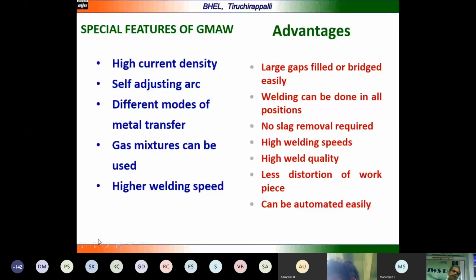There are 3 different modes of metal transfer in this process, which we are going to see in the subsequent slides. Gas mixtures also can be used in this process, and higher welding speed can be achieved. One major advantage of this process is we can go to higher welding speeds, even 800 mm to 1 meter per minute. If the parameters are set properly, we can achieve very good weld quality and welding profile.